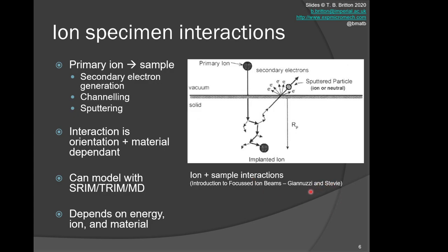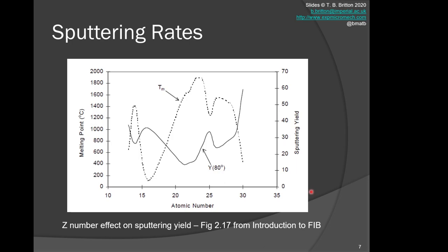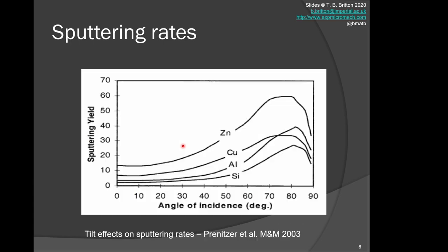A good cartoon is found in the classic Introduction to Focused Ion Beams book. One nice and problematic thing is that the sputtering rates of materials are effectively not dependent on atomic number. There are strong variations, and broadly it's inversely dependent on the melting temperature. You can see that inverse dependence here. That's useful and not useful, but it's one of the reasons why we get variable sputtering rates that can give us information about the material we're looking at.